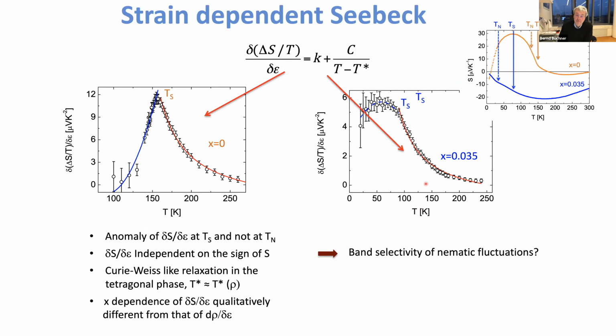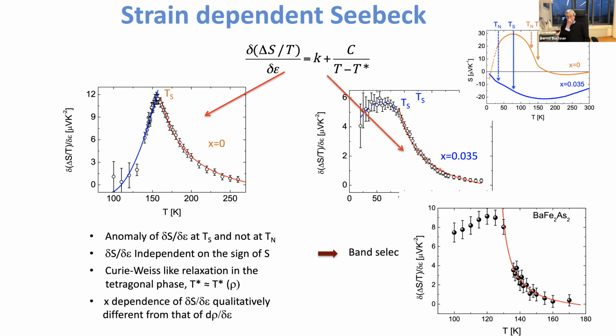Next thing is that in both cases, you can again fit these Curie-Weiss laws, and the Curie-Weiss constants which you obtain here are very similar to what you get from the resistivity. However, the x dependence of the size of the effect is different. So the Seebeck effect here is much larger in the parent compound than it is in the doped compound. So in that sense, already telling you that it's not straightforward to take the same susceptibility. And it's also maybe remarkable that when you do the same experiments on the barium 122, it's surprisingly similar. So that seems to be rather generic, this behavior, how this detail of the Fermi surface changes as a function of strain.